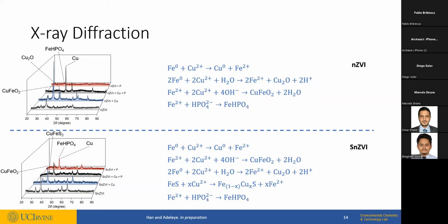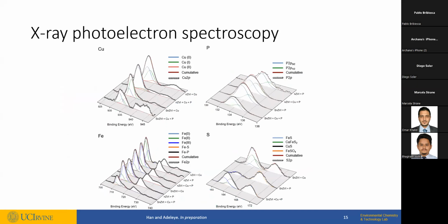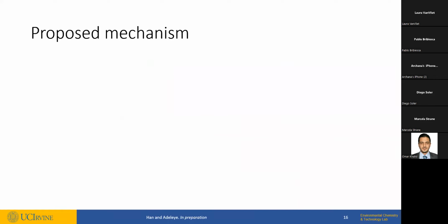And for phosphate, what XRD tells us is that there is the formation of iron 2 hydrogen phosphate, which is also a precipitate. So iron 2 has to be there for phosphates to be removed. And this is the primary mechanism for the removal of phosphate. And like I said, we also did XPS analysis, which I am showing you here. But the story from XPS is very similar. It actually just confirms the story from XRD.